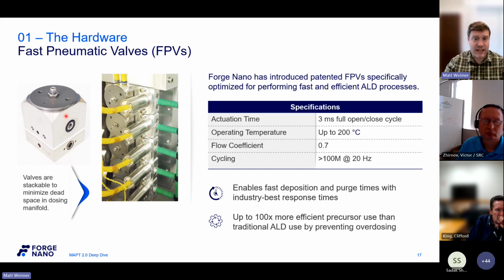These are made of primarily stainless steel. We can heat them up to 200 C, but what makes them unique is how fast we can actuate. Single direction, we can do about 1 millisecond. The full on-off is about 3 milliseconds. I use these in my lab, and we have recipes that run at 3 milliseconds quite reproducibly. These have also been running in a Department of Defense 200 millimeter fab for the past 12 years. And we know how reliable they are.